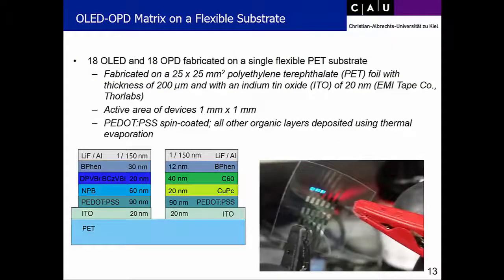So on the new devices now, and you can see a photograph here, we used as the emitter material, which is not very well readable here, again the DPVBI doped with 5% of BCzVBi. It's a 20 nanometer emitter material and has a blue emission, as you can see. Again, ITO was used as the anode for both of the devices. We spin-coated PEDOT:PSS as a hole transport layer, and then all the other materials are evaporated by thermal evaporation in the vacuum system. And so this is the OLED stack here.